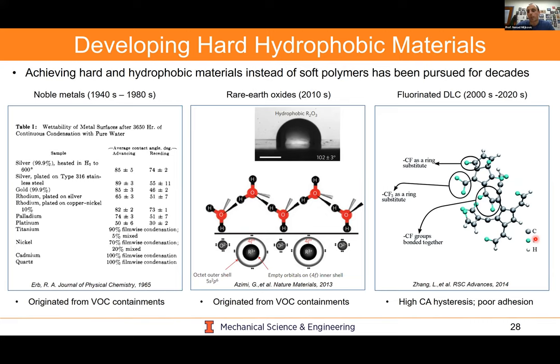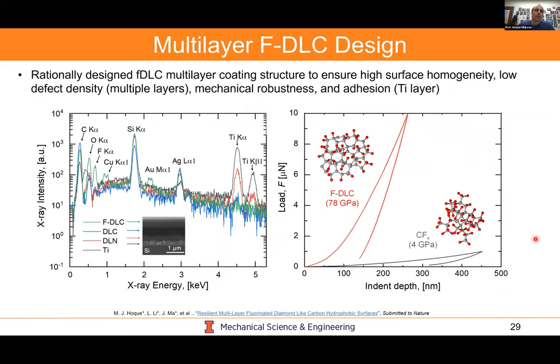And we asked the question, why can't we make this work, especially given that we have this new framework for durability? And so the material that we came up with that holistically takes into account defects, defect density, multi-layer formulations for forming tortuous paths from top surface defects to bottom surface defects, stress relief by gradient layers, co-deposition of fluorine in a top layer to form this FDLC. We actually call this coating FDLC, and this was developed in combination with a company called Oerlikon Balzers, which is based out of Europe. They're the biggest DLC supplier in the world.